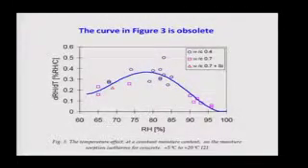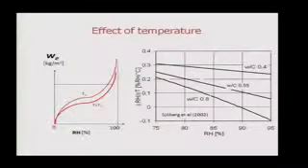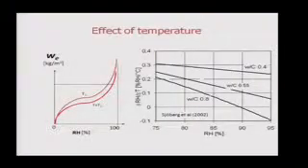I would like you to make a cross over that figure and say it should look like this instead — this is the new figure. The same data is included, but back then we didn't have more than this data here, so we drew a curve through the data. We didn't realize that we had one group with a certain water-cement ratio, and another group of data with another water-cement ratio. Later measurements show that there is a significant water-cement ratio dependence in this picture, so it should look like this with a very clear dependence on water-cement ratio.